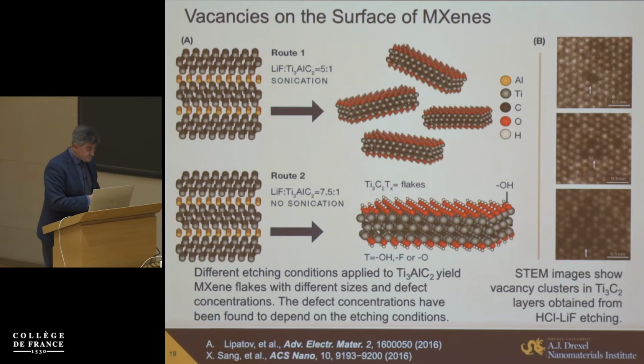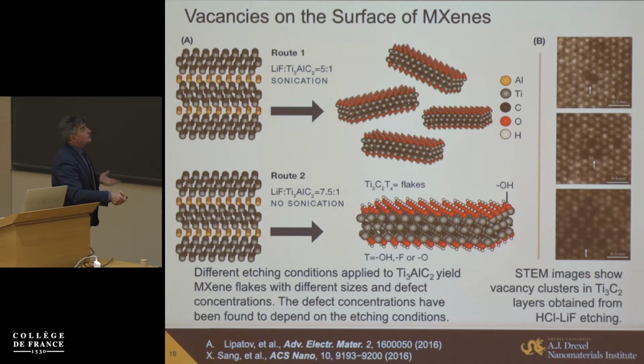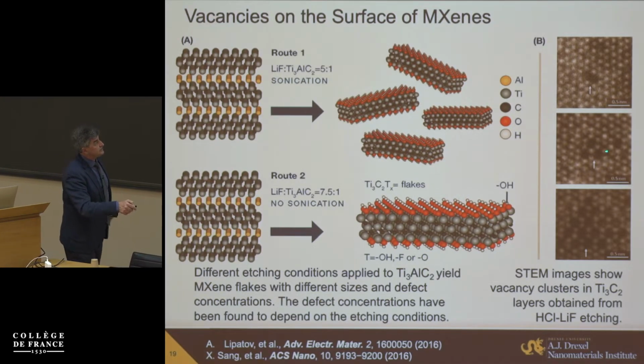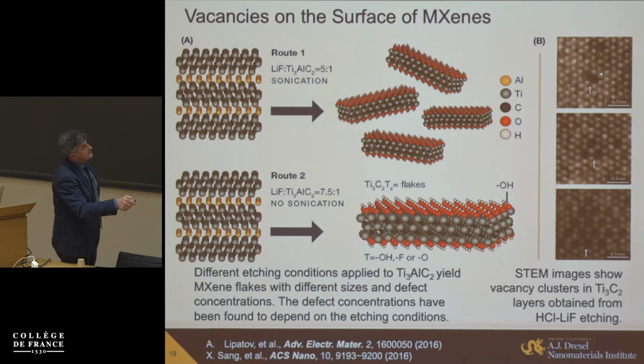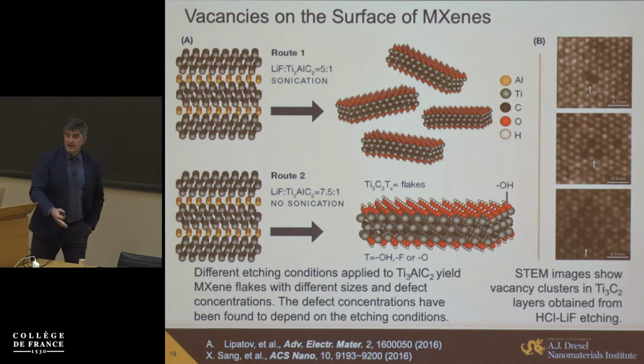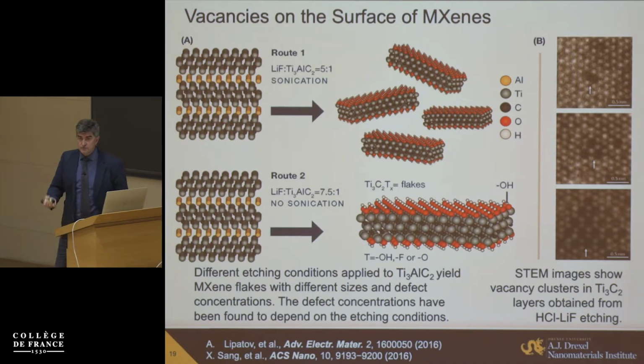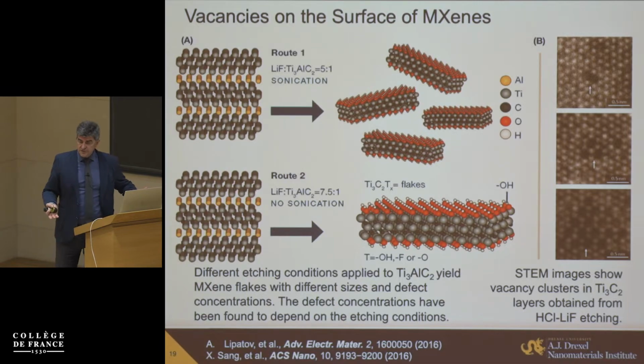And as I mentioned also, you can have defects in these materials here. For example, you can see vacancies in the titanium layers, single vacancy, triple vacancy, a cluster of vacancies, these dark dots that you can see in STEM images. Again, the harsher the etching conditions, the more vacancies you can get. And they're good for some applications.